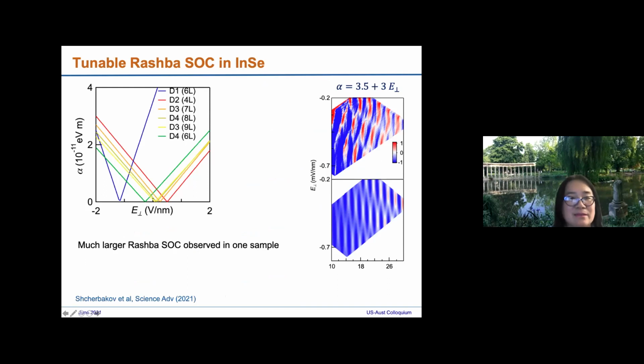This summarizes the alpha we find. For most of the samples, it follows kind of this pattern. This is maybe a strange unit if you're not used to looking at the spin-orbit coupling parameter, but it's actually not a small number. For example, it's a factor of 10 larger than in indium arsenide quantum wells.